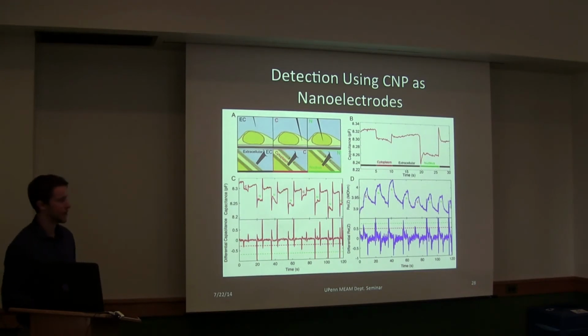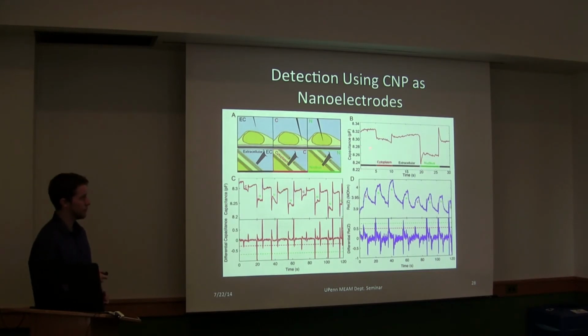But with the lock-in amplifier, we have excellent time resolution and excellent resolution of this technique. So we can actually detect these changes. And again, we get a significant difference between penetrating into the cytoplasm or the nucleus of these cells. So again, it's on the order of a 1.5 times greater signal change penetrating or probing the nucleus. And this is just a blow up of this trace showing that it's a very repeatable process.